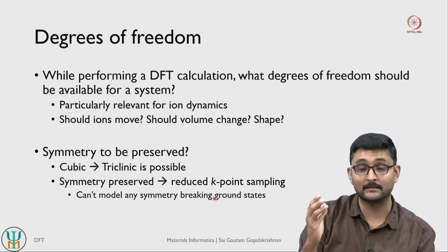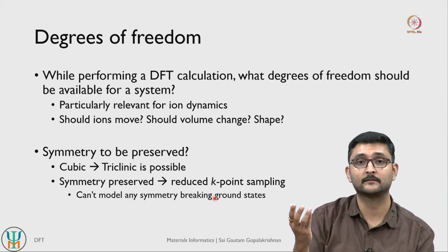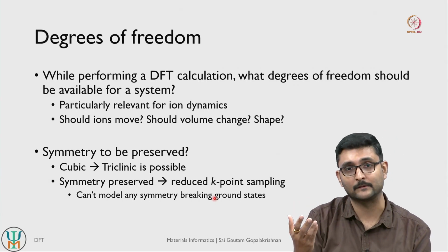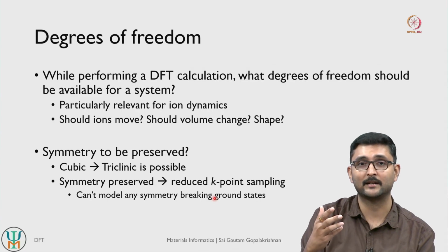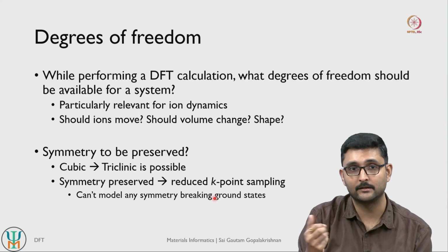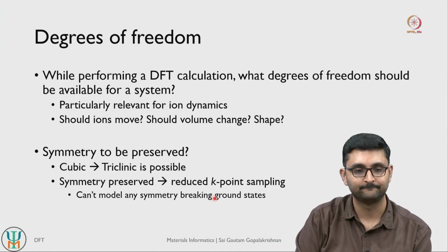But let us say your system has symmetry breaking ground states. So this is especially important for perovskite systems, piezoelectric systems and so on, and even magnetic systems, right. So if you have systems that actually break the symmetry to reach their ground state, then you have to break your symmetry, right. You cannot preserve your symmetry and expect to reach the right ground state.